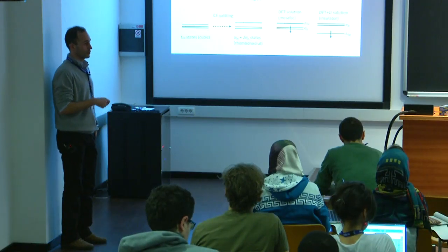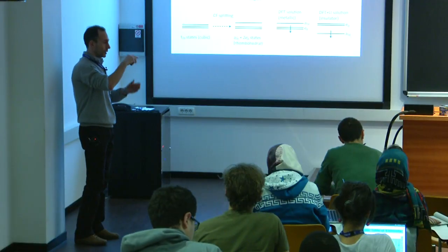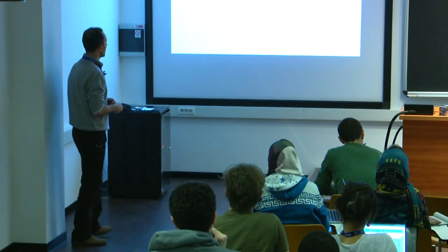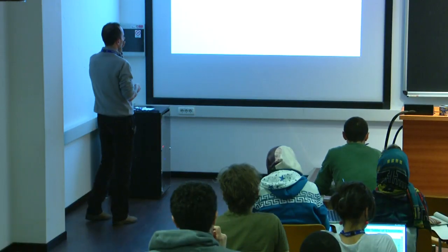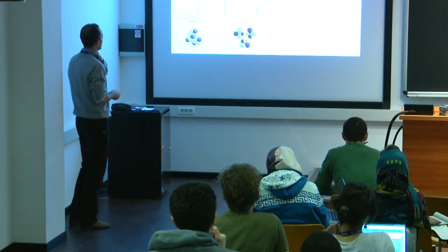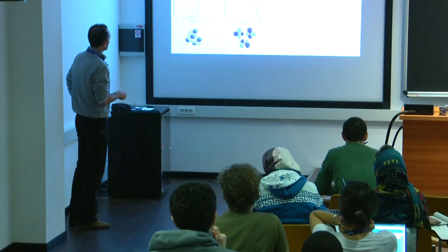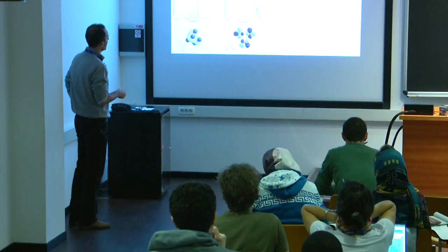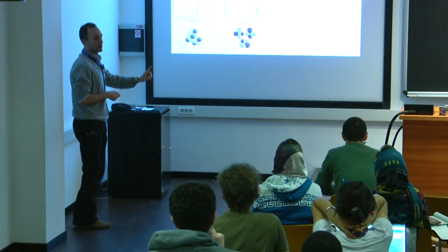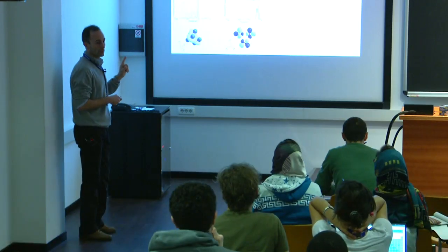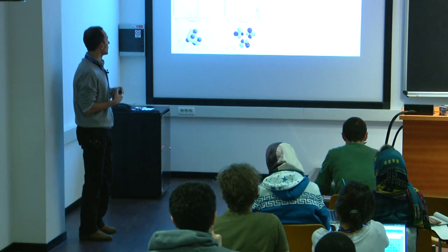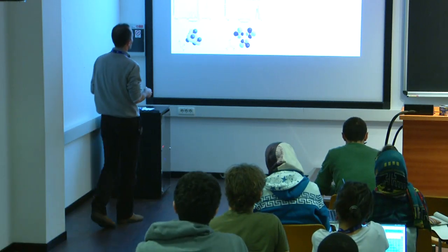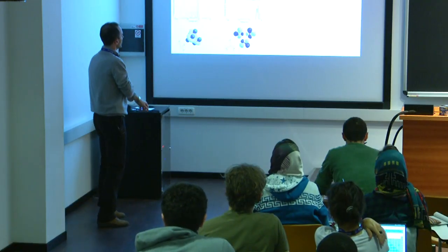And actually these terms are not right because, as I showed you before, the distortion is not the one that you expect from experiment. What's going on here, basically? This can teach us quite an important thing. So this is the +U solution when you localize the single electron on the state that remained single after the crystal field splitting. But nobody tells us that another picture is not the real one.